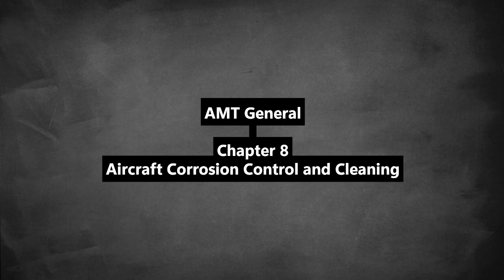Titanium. Generally good, but not totally immune. Correct. Very corrosion resistant, but salts and metal impurities, especially at high temps, can cause issues. Key rules. No steel wool, iron scrapers, steel brushes. Clean by hand polishing with aluminum polish or mild abrasive using only fiber brushes. Follow with a sodium dichromate solution. Wipe off excess. No water rinse needed.